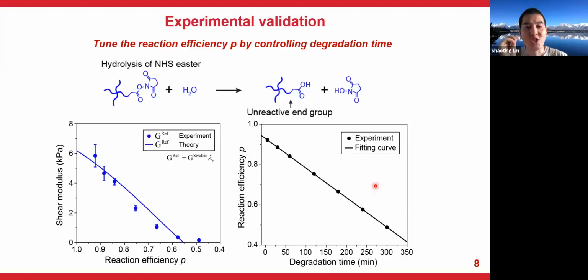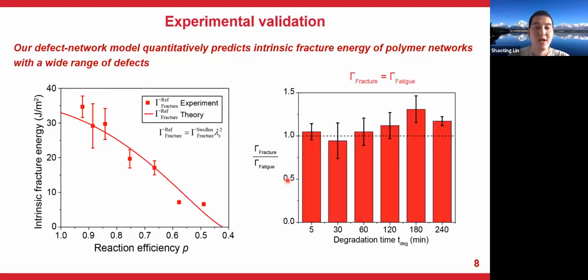And we further adjust one experimental parameter, the hydrolysis time, to allow the NHS ester to degrade over time, so that the reaction efficiency of the system can be readily tuned. So basically, if you let the system be stored for a longer time, the reaction efficiency of the polymers will degrade accordingly. Here we measure the shear modulus to calibrate the reaction efficiency, because the model for predicting shear modulus has been well established and validated in the field. And given the identified reaction efficiency, we can further calculate the intrinsic fracture energy based on the amount of the macromers with various orders of dangling chain in the systems.